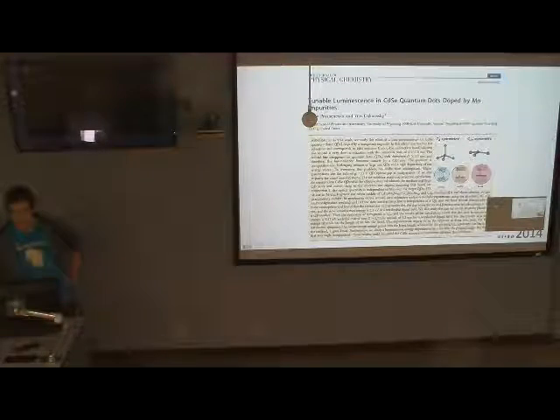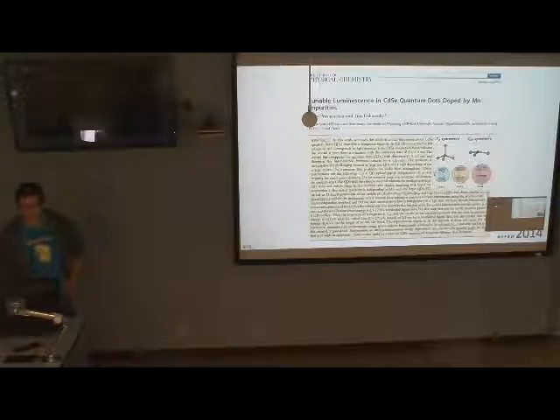And then applying his method, he's seeing the splitting between the d levels of manganese versus whatever your levels are for the atoms surrounding the manganese. You can take the smallest bonds which you have in your lattice and create the lattice of cadmium selenide, or whatever his quantum dot is. It's a wurtzite structure, so it means you will have 4 neighbors. Oh, 4? Okay. I thought it was octahedral. That's rock salt. Okay, whatever the symmetry of this lattice is, you take just this small piece of your crystal, and the only thing he was really looking at is the splitting between d orbitals.